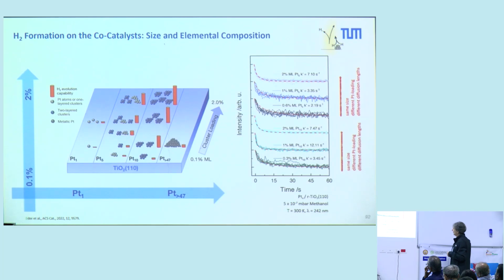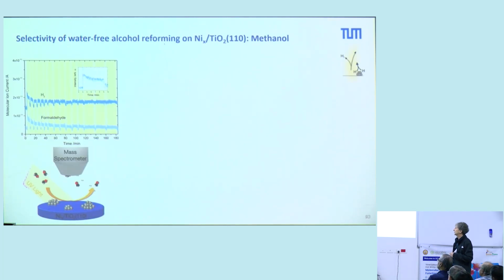Then, of course, you can also increase the cluster coverage. Of course, you have more platinum. You produce more hydrogen, but you also decrease the diffusion length. And so we have a higher reactivity. This is true for platinum 5. We see this increase. For platinum 10, it seems to saturate at the given coverage.